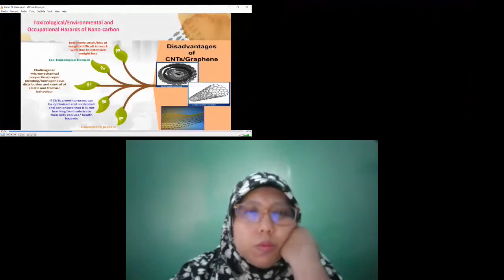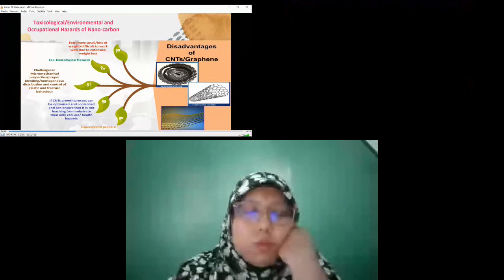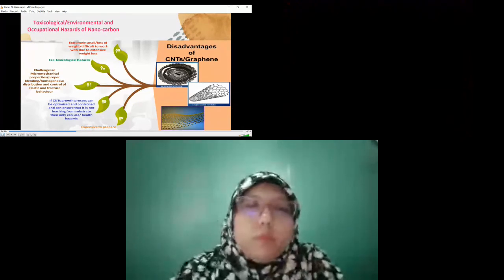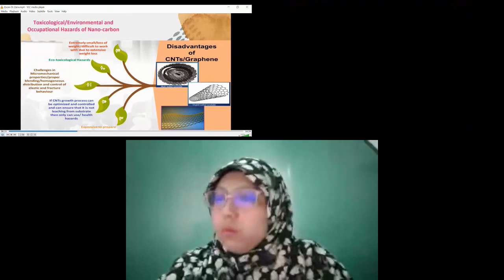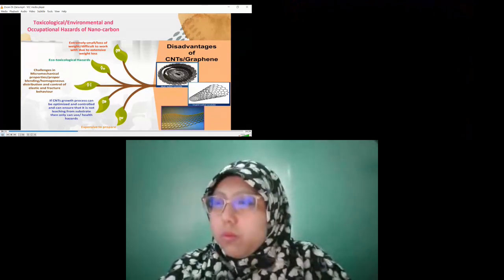Now what is the disadvantage of CNT and graphene? As I told earlier, the adsorption process needs separation of the carbon. This is difficult for CNT and graphene, and weight loss is there. And then we have to control their surface functional group. If the growth mechanism is not controlled, then over the CNTs we can get some metallic pollutant. So we are introducing secondary pollutant in nature.